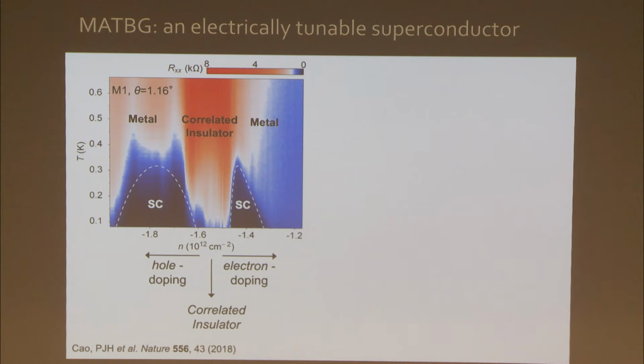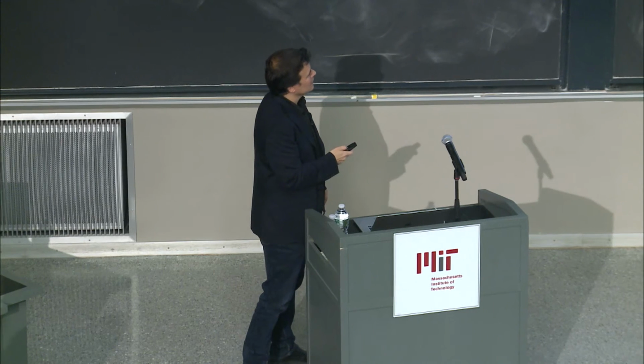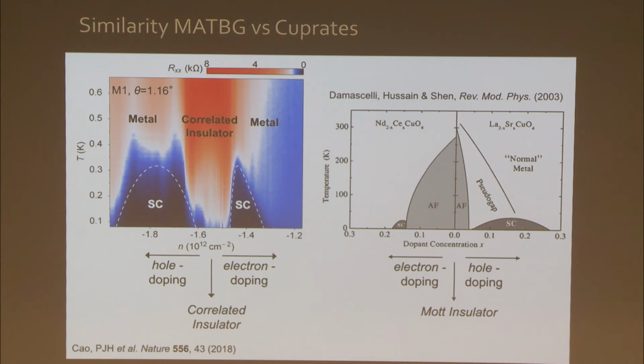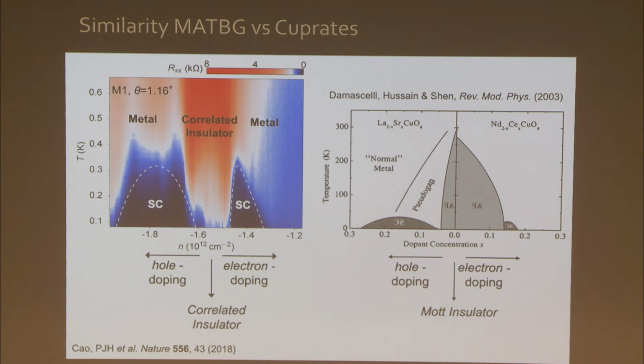Now, when my students showed me this data, I was immediately shocked, because it reminded me of the hundreds and hundreds of times that I had seen at seminars and talks this type of phase diagram, okay? This is the phase diagram of the high-temperature cuprate superconductors, okay? For the high-temperature cuprate superconductors, here, this zero doping means 1 electron per copper atom, as I mentioned earlier, okay? So 0 means actually 1. Then let me flip this axis so that they are in the same orientation as this, okay? So if you add 1 electron per copper atom, you have a correlated insulator called a Mott insulator. If you dope with holes, if you remove electrons, you have a superconductor. If you dope with electrons, you have another superconductor.